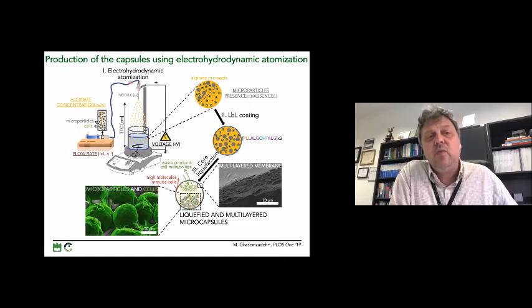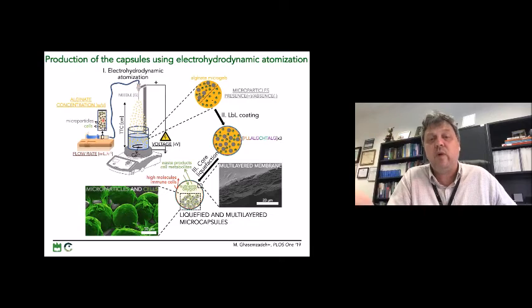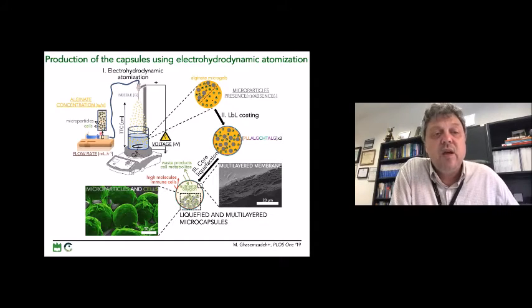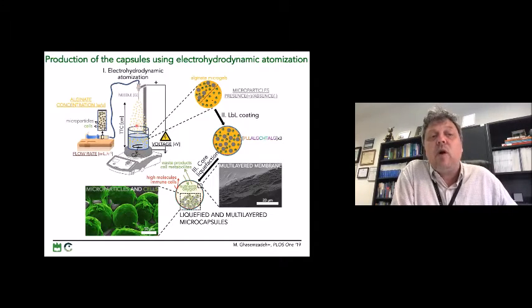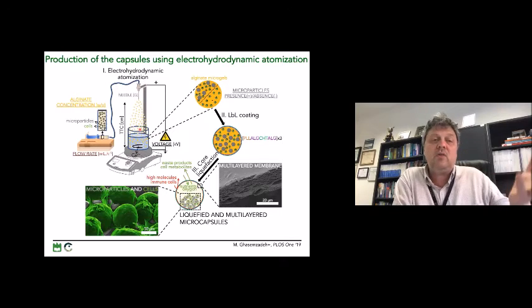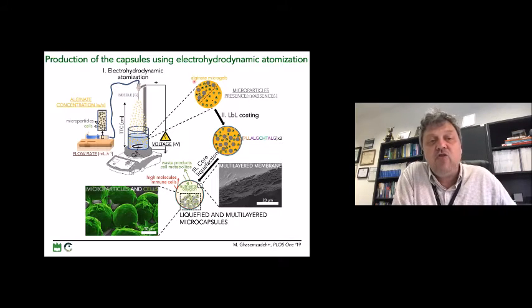So in this case, we just spray micro droplets of these alginate solutions that contain cells, the microparticles, all the ingredients that we want to have in the final capsules. So these liquid droplets will be jellified when they contact these precipitation baths that contain calcium ions. So the calcium will cross-link the alginate, and so we can generate microbeads of alginate that contain the cargo that we want.